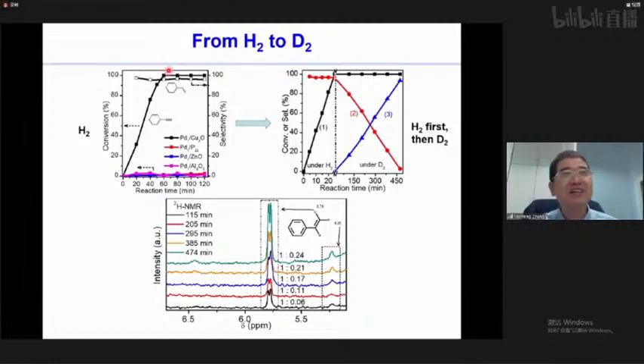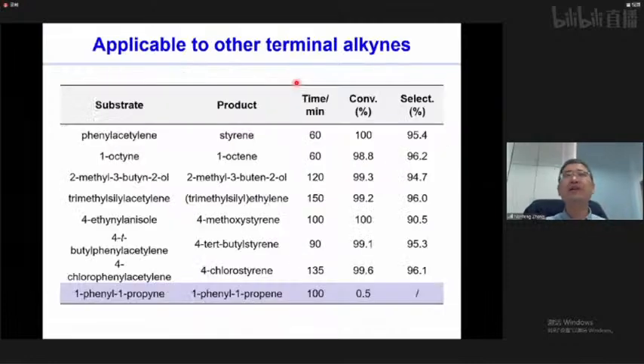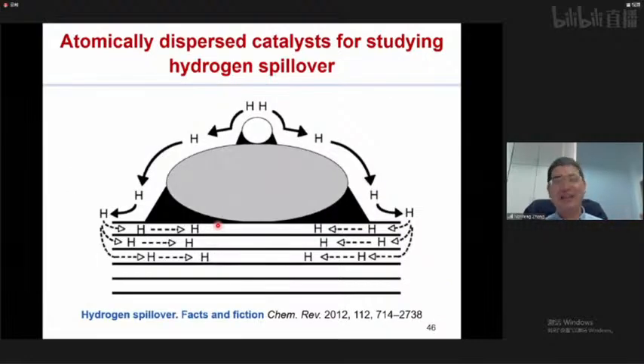So if we have the addition of the third hydrogen, which means that the double bond should be open, right? And then the single bond should be rotatable, okay? So we found that after we replace the hydrogen atmosphere with a D2 atmosphere, we did see that we can do the hydrogen and deuterium exchange. So this really proves that our DFT calculation result is correct. We do have the addition of the third hydrogen, but not the fourth one. So after this understanding, we found that this catalyst is highly active for all kinds of terminal alkynes. Okay, so this is quite interesting.